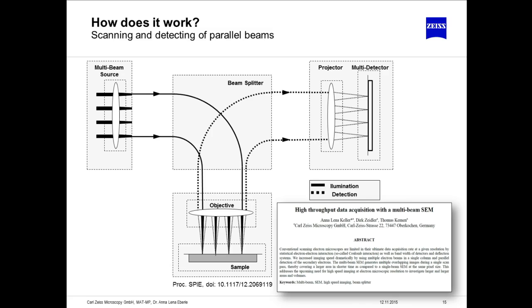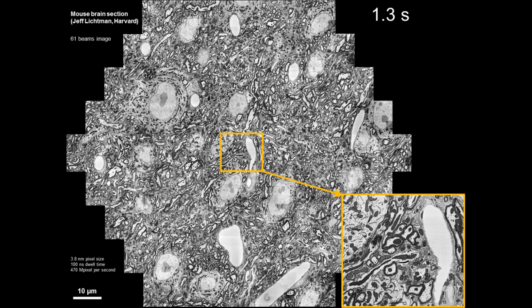This is an example of an ultra-thin mouse brain section we get from Jeff Lichtman from Harvard University. This is a 61 beam image, which is merged to one field of view, and it's taken at about 4 nanometer pixel size, 100 nanoseconds dwell time, which ends up in about 470 megapixels per second, because this whole field of view is imaged in just 1.3 seconds. And to give you a little bit of an idea how large this field of view is, we have about 110 microns from left to right and about 100 microns from top to bottom. So this is the field of view that we image at once.